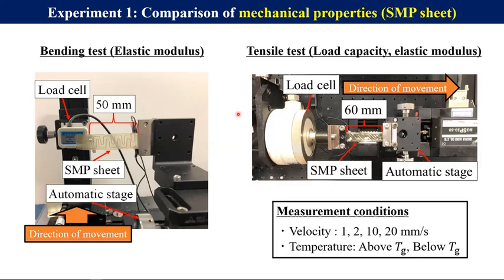Here is experiment 1 in order to compare the mechanical properties of two SMP sheets. In the bending test, one side of the SMP sheet was fixed to an automatic stage, and we pressed it against the load cell to measure the elastic modulus. And when it comes to tensile elastic modulus, it was measured by fixing each end of the sheet to a load cell and an automatic stage and pulling. Measurement conditions for both of them are here.